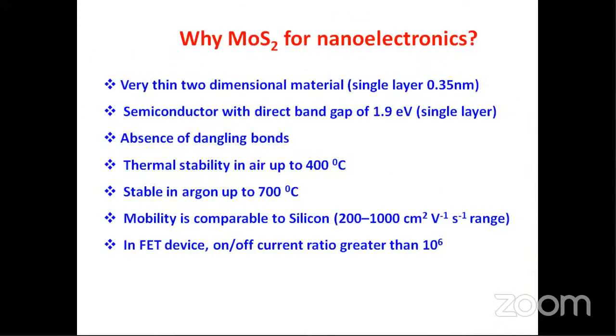And why I am interested in MoS2 for nanoelectronics is the stability of this material: in air it is stable up to nearly 400 degrees centigrade, and the stability is very high compared to silicon and other materials, nearly 700 degrees centigrade in argon. For any electronic device, the most important property is the on-off ratio. The on-off ratio is very good compared to other semiconductor materials. As for mobility, graphene is very high, nearly 10^5 cm² per volt per second. In the case of MoS2, mobility is nearly 200 to 1000 cm²/V·s.